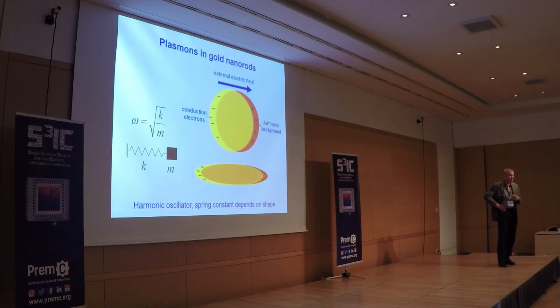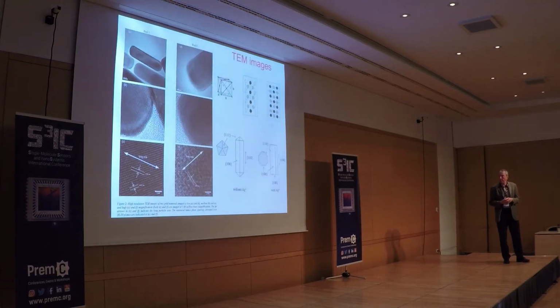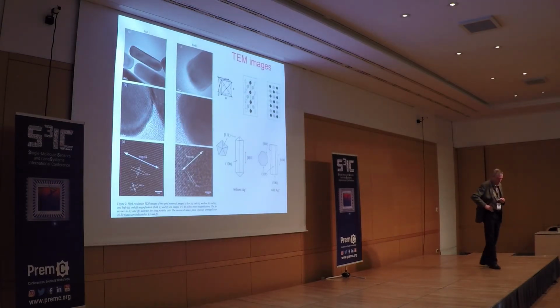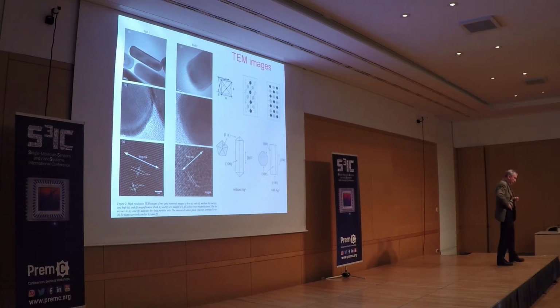So you have the resonance frequency, that's the plasmon resonance, which in the case of gold happens to occur in the visible. For spherical gold nanoparticles it is in the green at about 500 or 530 nanometers, slightly size dependent. Whereas if you move towards elongated particles like rods, you can shift these transitions all the way down to the near infrared, 1 micron, even longer if you take gold nanowires, which have extremely large aspect ratio, very long dimensions. All right. So these gold nanoparticles, gold nanorods and nanospheres, are usually in our group nowadays commercially available, but